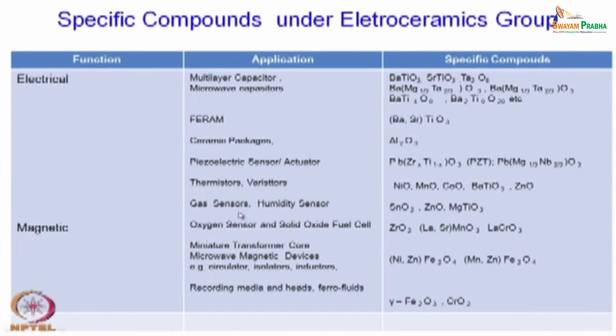The semiconducting property of some of the oxides can also be used for sensing the presence of gases, particularly reducing gases or combustible gases. So, gas sensors can be made by exploiting the variation of electrical conductivity as a function of gas concentration of oxides like tin dioxide and zinc oxide. Then there is the humidity sensor. Humidity can be measured by porous ceramics like magnesium titanate or aluminum oxide, and there you measure the variation of capacitance as a function of relative humidity of the environment.